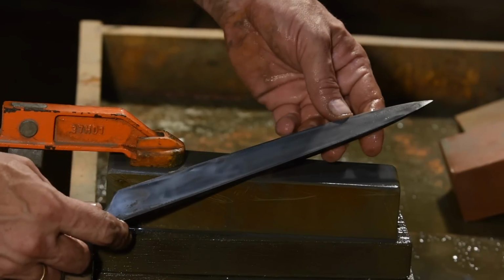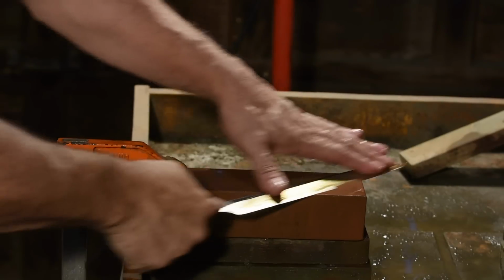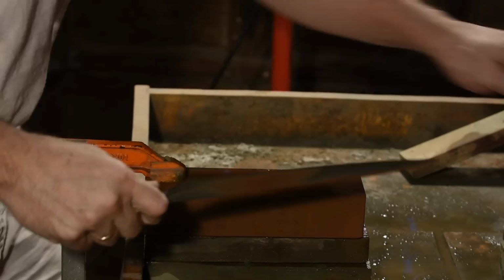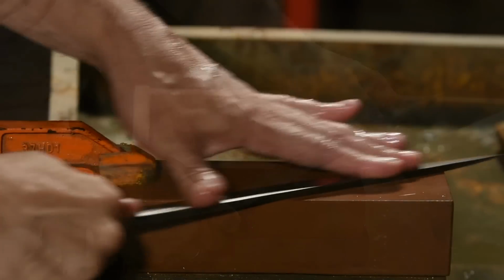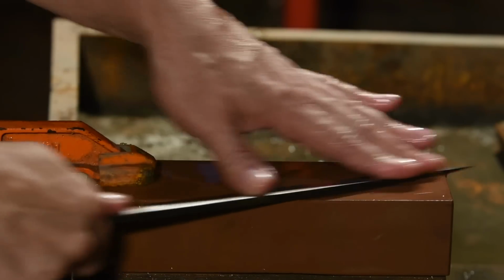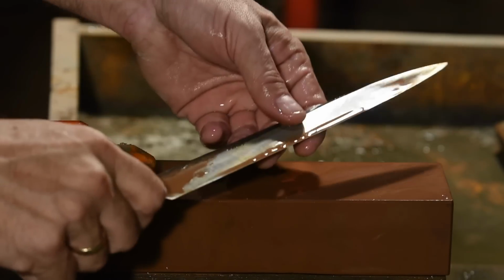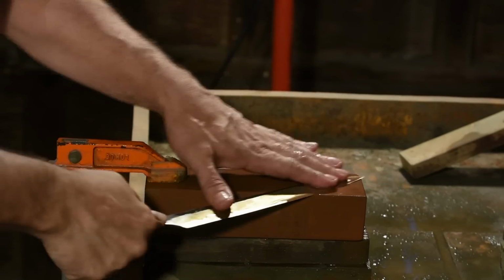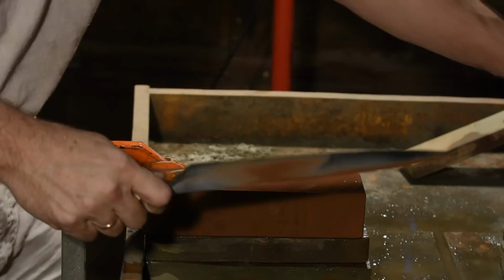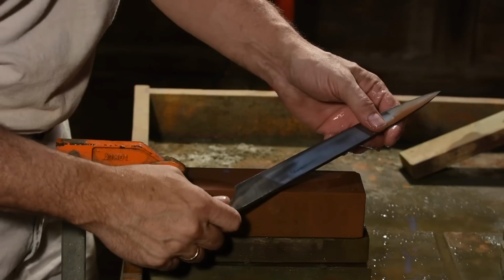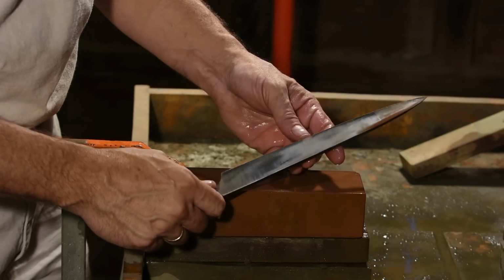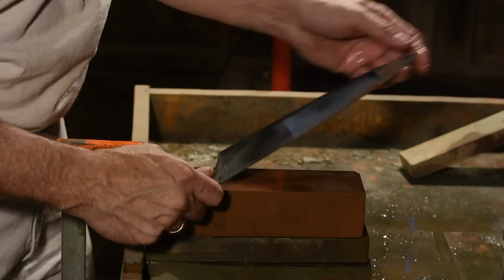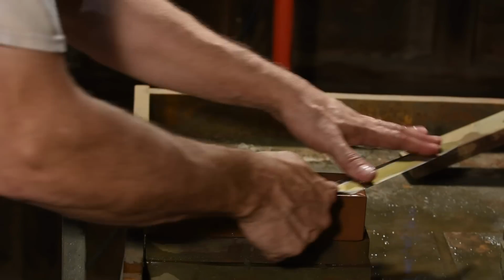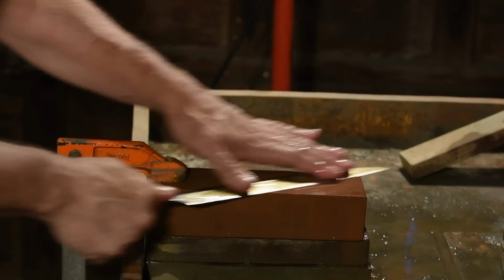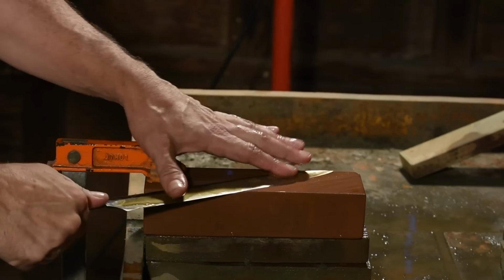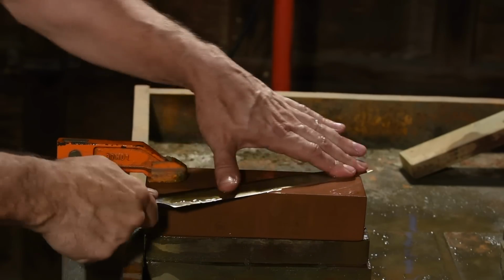And once I've got a nice sharp edge, then I'll turn to a 1200 grit stone. I put a little baking soda in the water, which keeps it from causing the steel to rust. Now, Japanese water stones are made up to extremely high grits, so if you want, you can keep sharpening up to whatever grit floats your boat. There are water stones that go up to 10, 20, 30,000 grit if you have the urge to go that far. But me, I'm quitting at 1200 grit, and believe me, this is already outlandishly sharp.